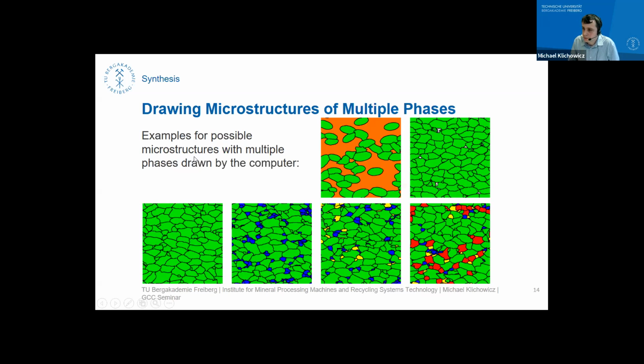But what else can we do? Of course, we can draw microstructures with a matrix, that is, for example, this orange phase here, or we can also create pores like those gray structures in this microstructure, and we can add as many phases as needed. For example, we start here with a monomineralic microstructure, which is indicated by all the green grains, and then we add a blue phase, which has smaller grains, and a third yellow phase with small grains, and here we have a fourth red phase with some bigger grains. So we can create random microstructures with as many phases as we want.